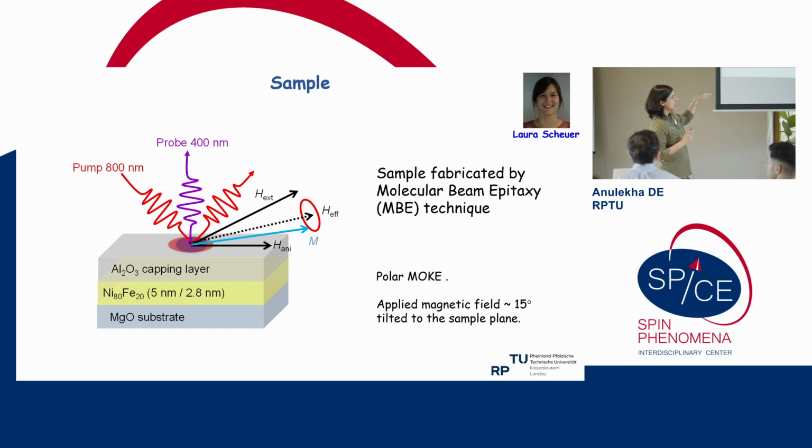They are deposited on an MgO substrate with an aluminum oxide capping layer. The samples are fabricated by molecular beam epitaxy. Basically, Laura fabricated the samples. We have done the measurements in polar MOKE geometry with a slightly tilted applied magnetic field, and we have used an 800 nanometer laser to pump and 400 nanometer to probe the system.